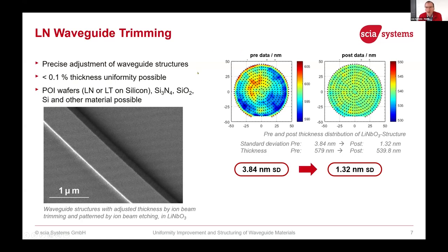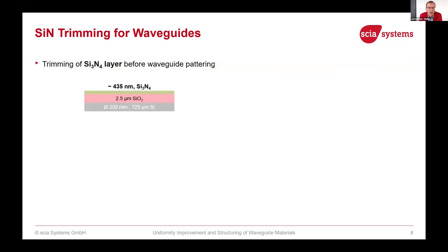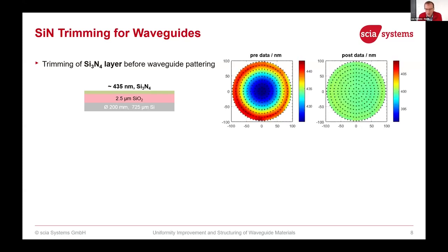You see the pre-data in the left picture with some variation in the thickness, with a standard deviation of 3.84 nanometer, and this could be trimmed down to 1.32 nanometer standard deviation with our ion beam trimming process. Also, silicon nitride is a material that can be trimmed. Here's an example of a silicon nitride film of 435 nanometers on average on a 2.5 micron silicon oxide film on a wafer. Here, even the pre and post data comparison.